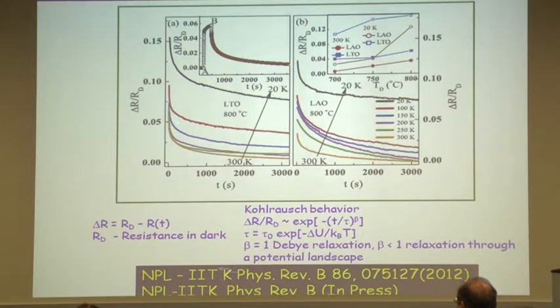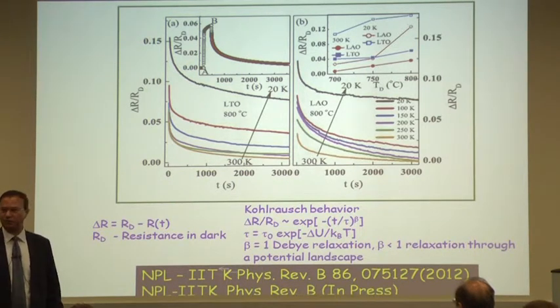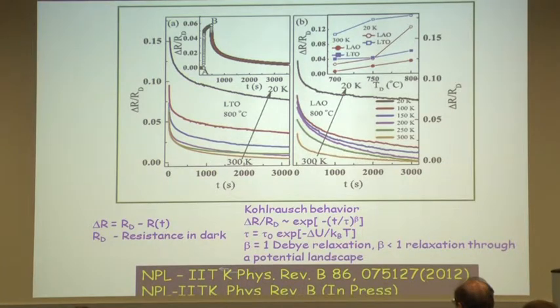And it turns out that the dynamics is essentially the same. It does not matter whether you have LAO on the top or you have LTO on the top. The dynamics of the 2D gas is essentially the same. The superconductivity is the same. The magnetoresistance is the same.